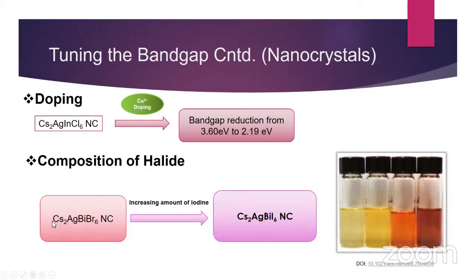So basically here you can see one example, like we have started with Cs2AgBiBr6 nanocrystal, and then we have done the anion exchange. And from here we are actually getting the Cs2AgBiI6 nanocrystal. If you see in this picture, in this solution there is no iodine, and if you are increasing the amount of iodine, as a final product you can see a significant color change. So in this solution, the content of iodine is maximum.